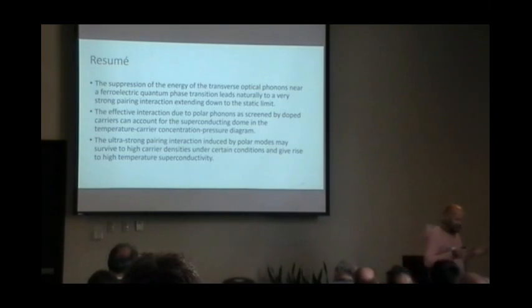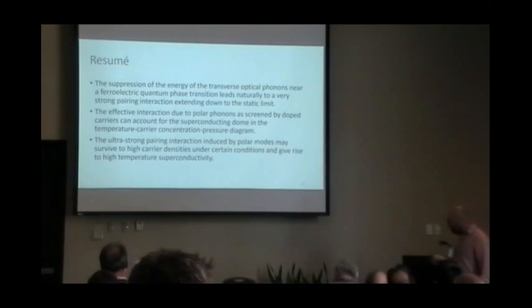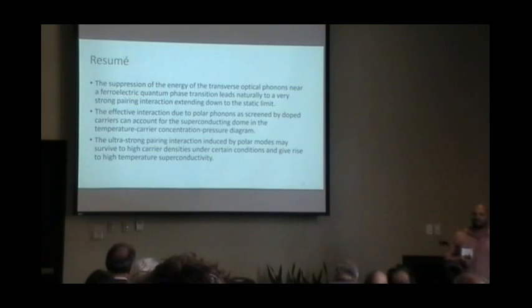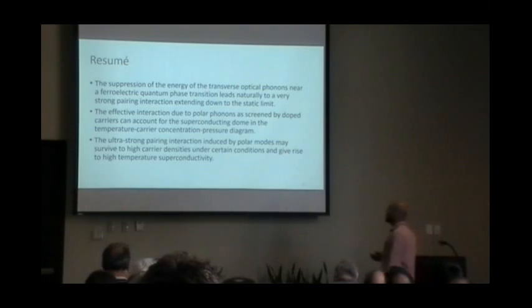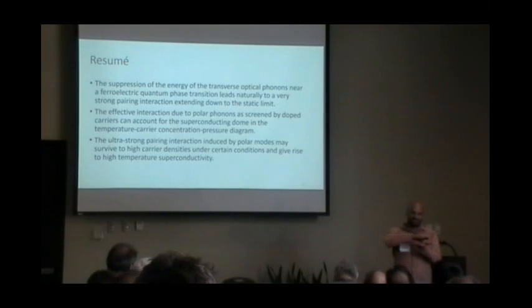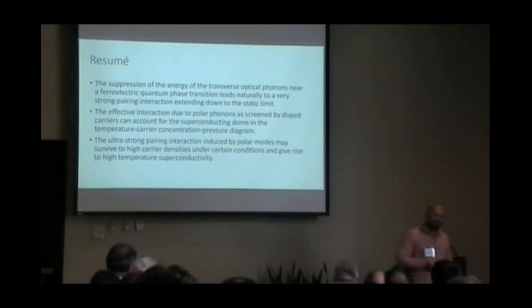So one really important question now is, is this interaction possible? Is it possible to transfer this interaction to other materials where you might have a higher critical temperature, where you have higher electron density? Probably not so much in the case of materials that are close to a ferroelectric critical point, but maybe to materials that are close to an anti-ferroelectric quantum critical point, which is less sensitive to the screening of the electrons. Otherwise, there have been experiments where they put iron selenide on strontium titanate, and they raised the critical temperature by a factor of 10 or something, or 8, I think. And so this might very well be related to the coupling to the modes in the strontium titanate.